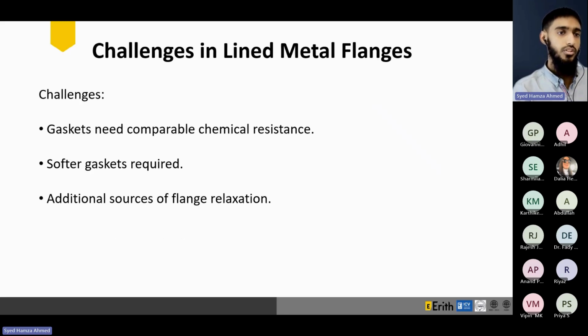So, talking about the lined metallic flanges, gaskets for flanges with this type of liner need to provide comparable chemical resistance to that of the liner. So basically, the liner that is chosen for the severe chemical service. If you're putting in a gasket that cannot handle the severe chemical service, there's no point in putting it in a piping system. The gasket also needs to be soft enough to avoid compressing the liner and easily sealed as well.